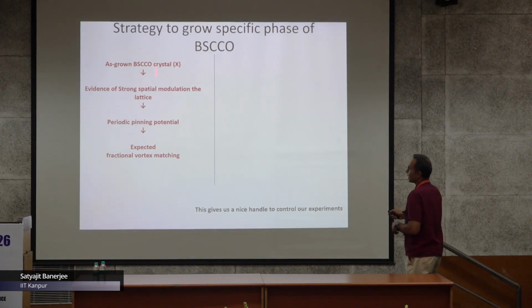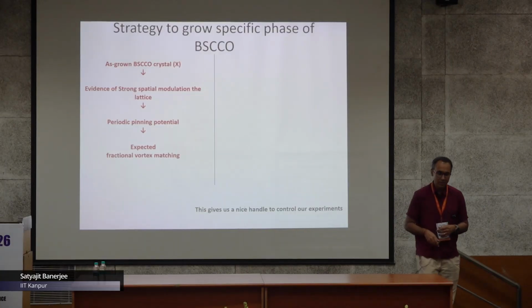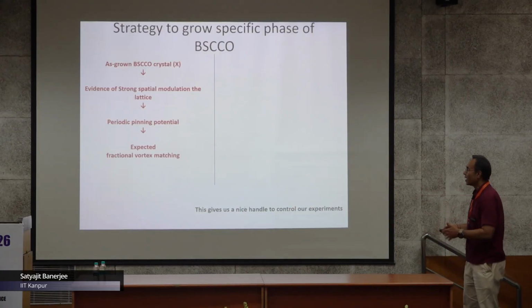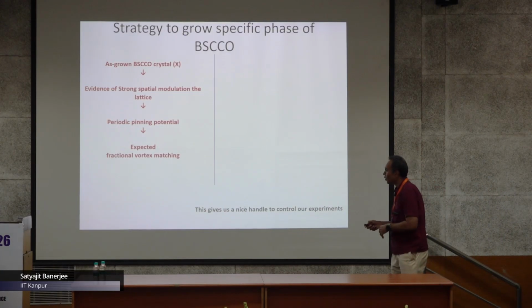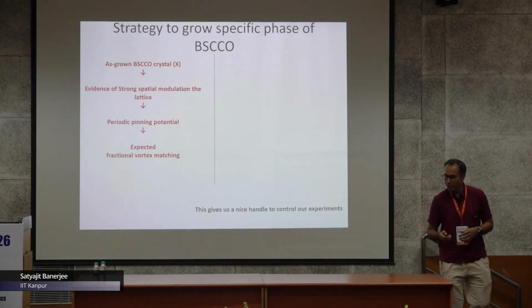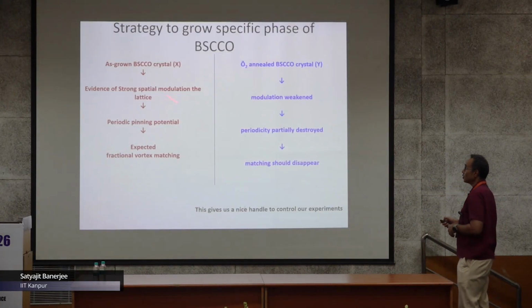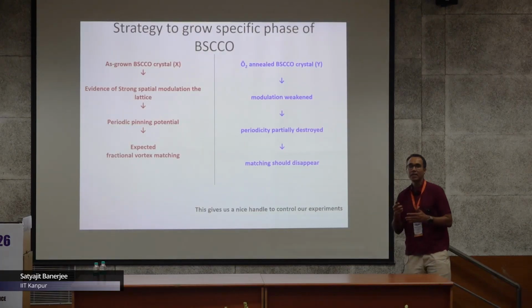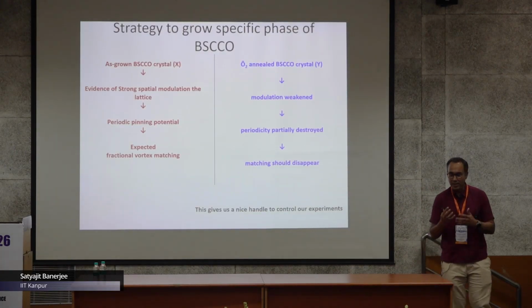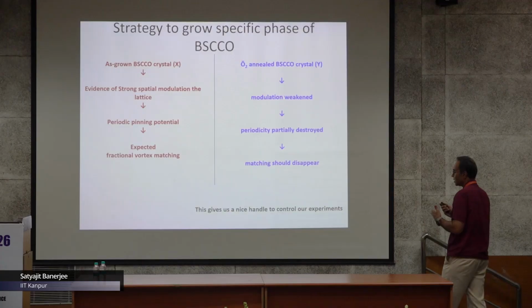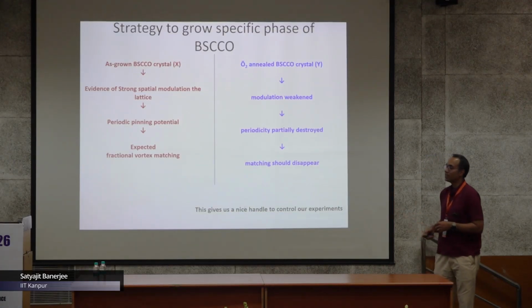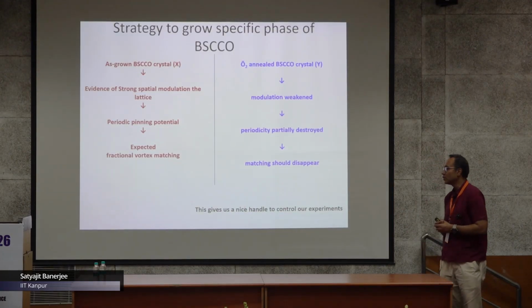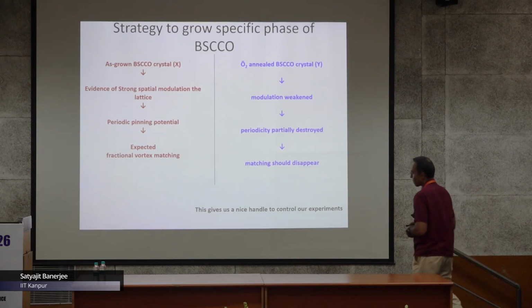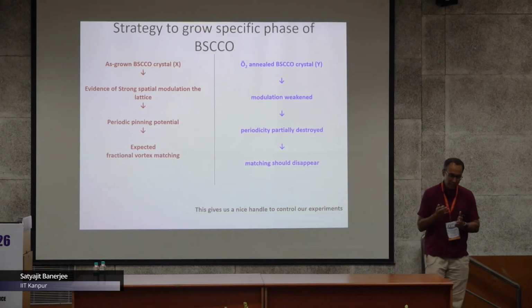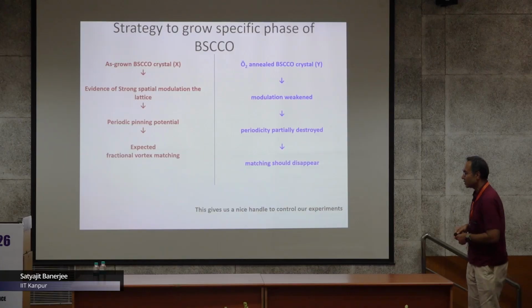We will look at some results on these high quality single crystals of BSCCO 2223, and then we subject these crystals to different annealing procedures, with oxygen annealing or temperatures in certain specific recipes, and we will see what happens to the flux distribution inside these systems. It turns out this becomes a nice handle to actually control the flux distribution inside the superconductor.